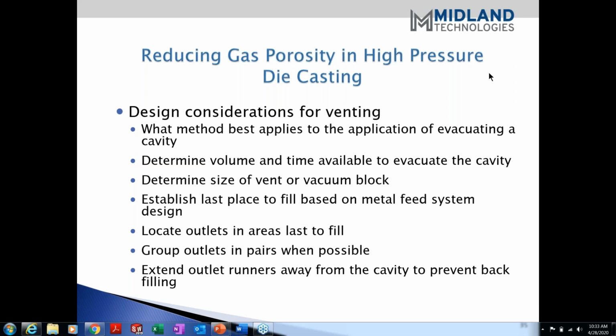So determining the volume and the time available to evacuate the cavity is critical. Determining the size of the vent and the vacuum block, obviously that's pretty critical. And there's a difference between the two areas. To establish the last place to fill, as I mentioned earlier, can be accomplished in a number of methods. The best method, of course, is to use some type of simulation program to assist you in establishing that location. Locate outlets in the areas last to fill, as I mentioned.